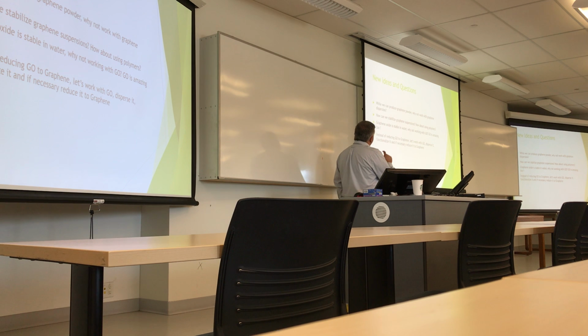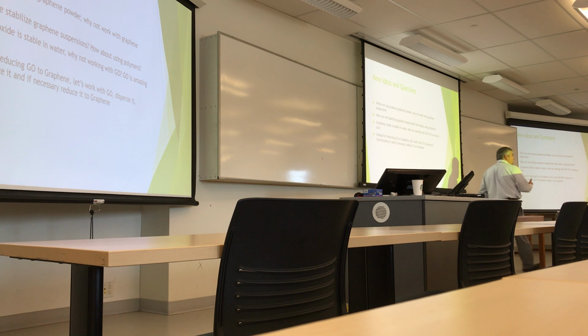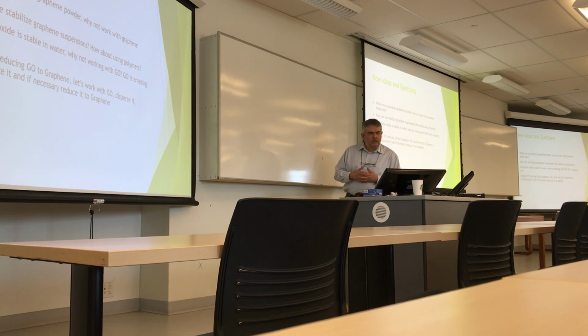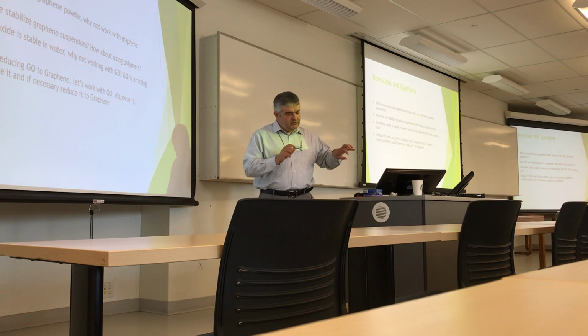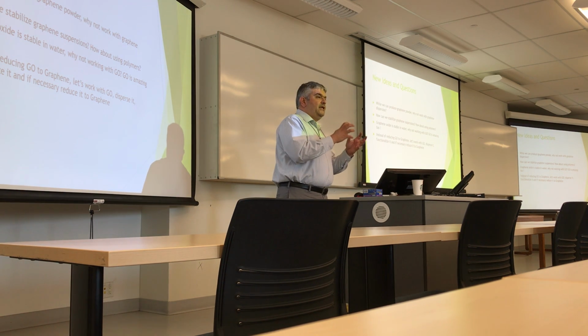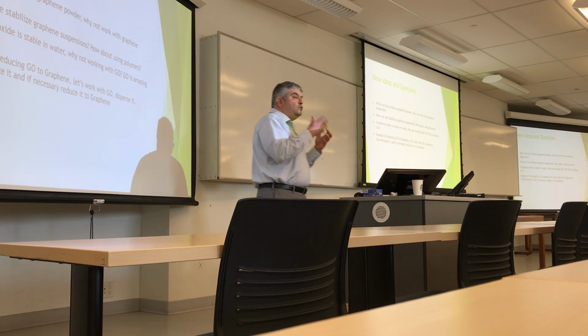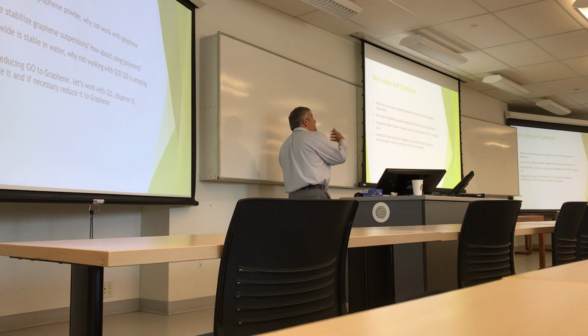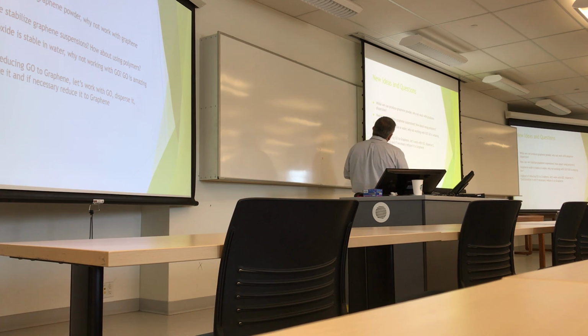After doing some research, we started thinking again. As I said, the conventional method was working with nanopowders and trying to separate them and make the exfoliation and intercalation. But since the way that we produce graphene was through a dispersion, we said, okay, instead of making a powder and then putting it back in the polymer, let's work with the dispersion and see how we can put it together with the polymer in the dispersion phase. So the question was how we stabilize graphene suspension, and we addressed it.